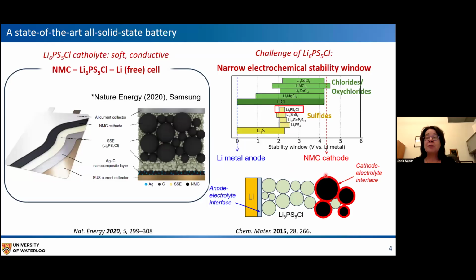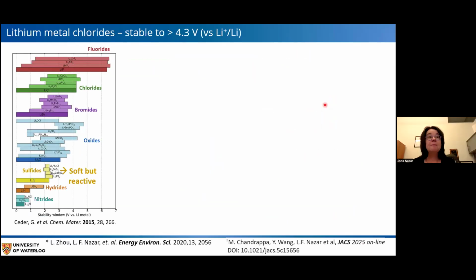And these coatings, quite a plethora of them exist, usually lithium niobate or lithium zirconate, but they can be difficult to apply. It requires an extra processing step, and they don't necessarily achieve ideal coverage. So it's something that one would like to avoid. And one can do that by using these chlorides and oxychlorides, which have, according to calculations carried out by Gerbrand Ceder's group in 2015, oxidation potentials that make them compatible with the NMC materials and other types of high voltage cathodes.